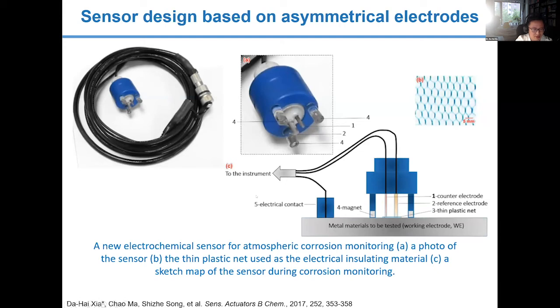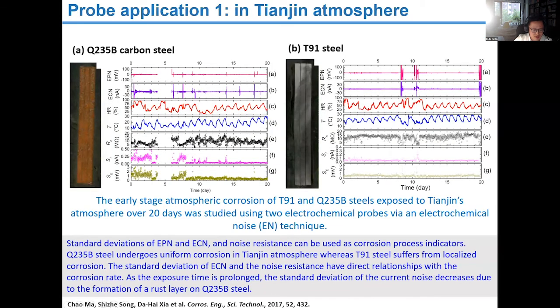Okay, this is a monitoring result for field corrosion monitoring, and it shows 20 days of results for two steels. One is carbon steel, and the other is T91 steel. As shown here, humidity is low. The current noise and potential noise amplitude is very small, only a few nano amps and millivolts respectively, indicating that the corrosion rate is significantly low.